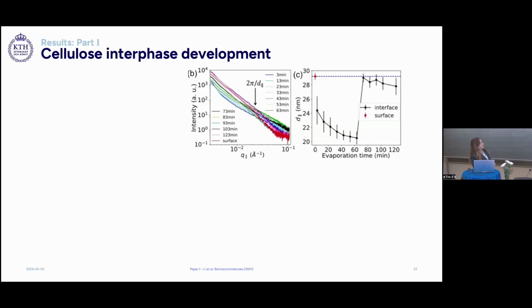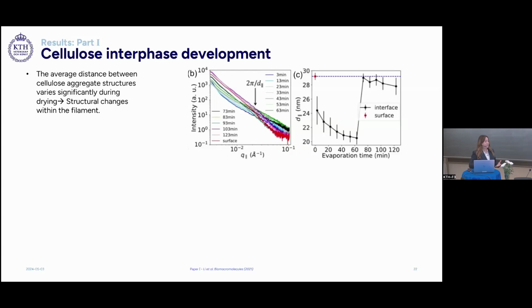The curve on the left shows the intensity curves obtained from the horizontal integrations of the 2D patterns at different evaporation times. From these curves, we're able to extract a characteristic length scale, which is plotted against the evaporation time in the next figure. This gives us an idea about the average distance between cellulose aggregate structures, which varies significantly during drying. And this means that we have structural changes in the filament during drying.